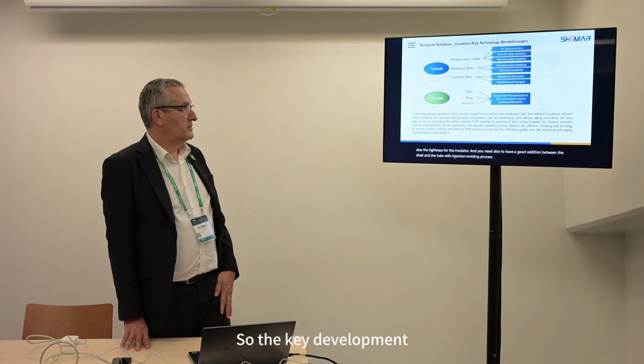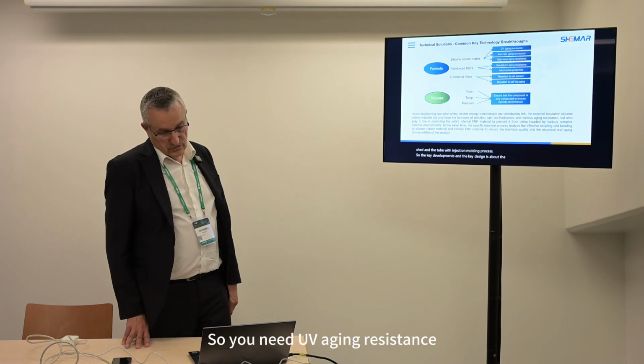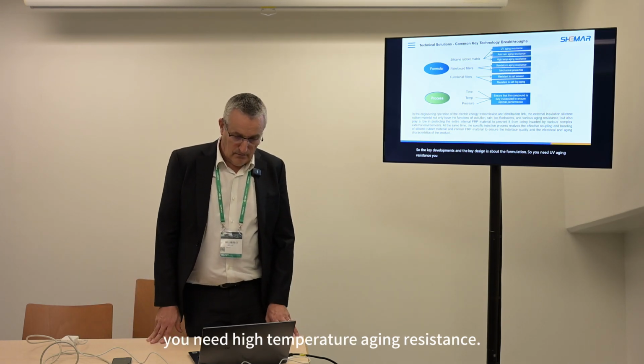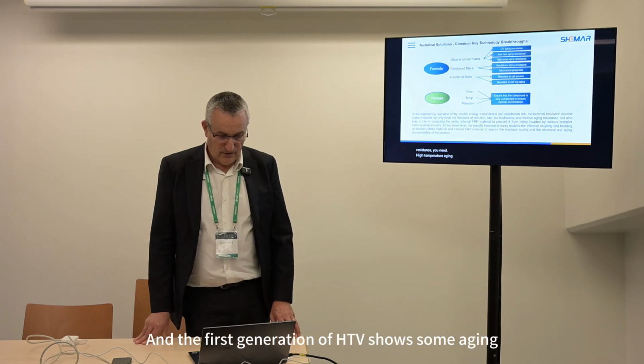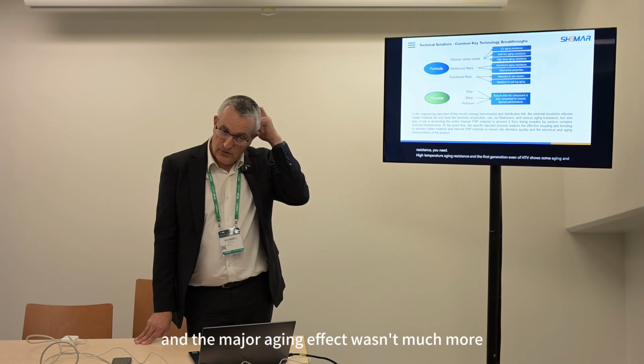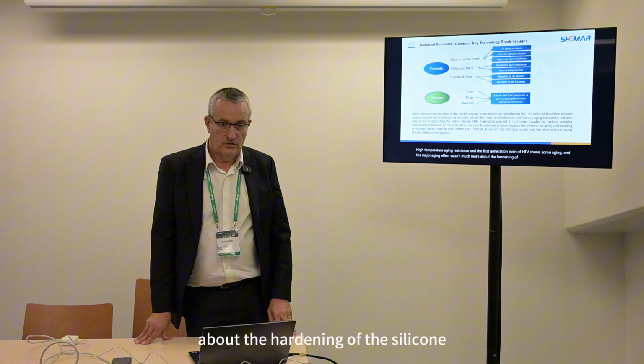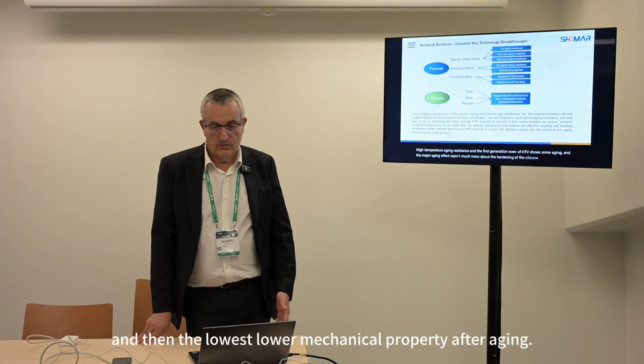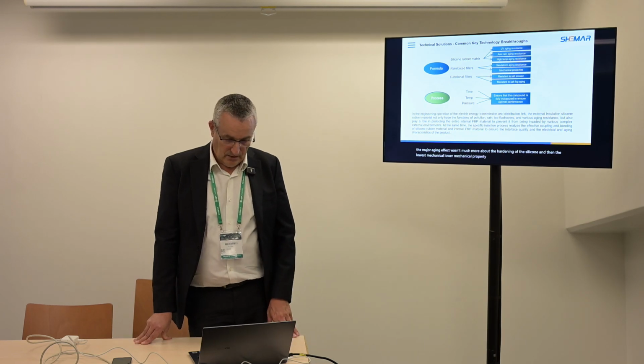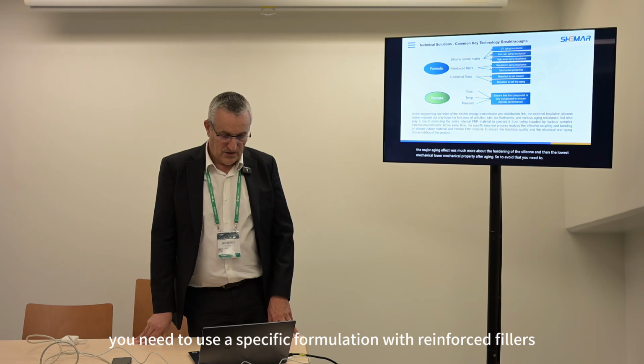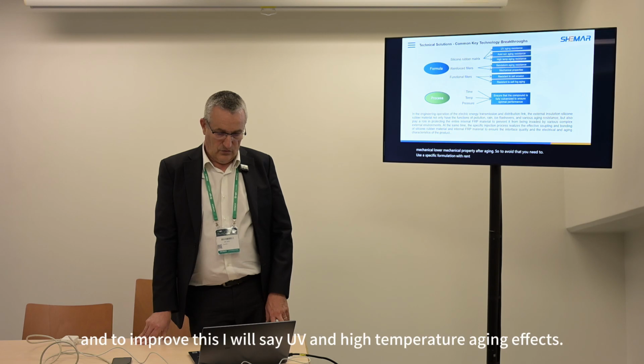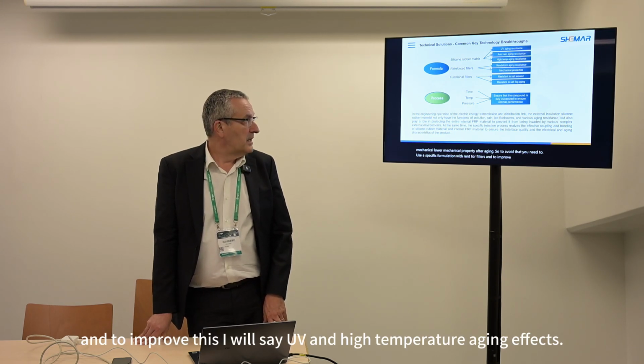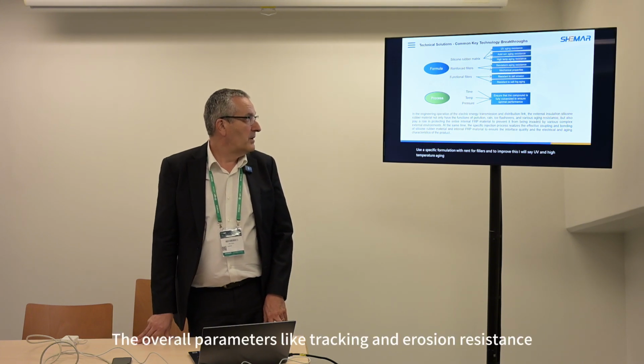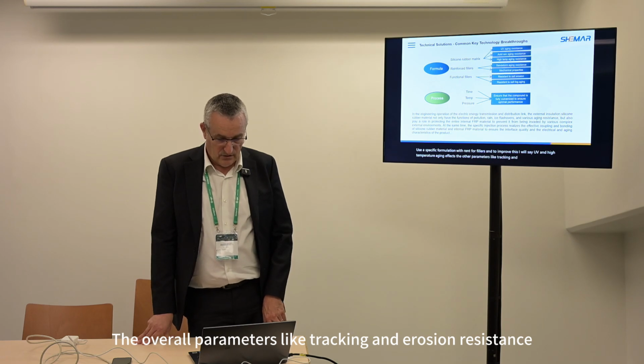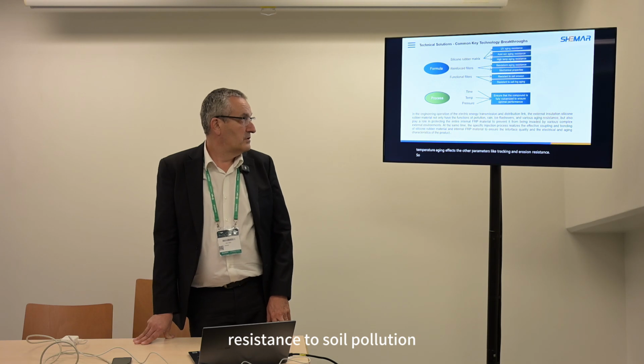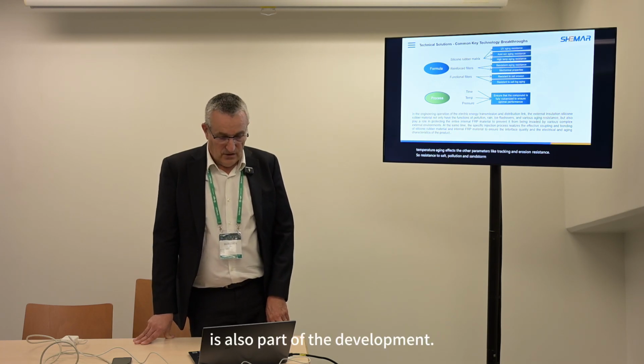So the key development and the key design is about the formulation. You need UV aging resistance, you need high temperature aging resistance, and even the first generation of HTV showed some aging, and the major aging effect was the hardening of the silicone. So then lower mechanical property after aging. To avoid that, you need to use a specific formulation with reinforced fillers, to improve the UV and high temperature aging effects. The other parameters like tracking and erosion resistance, resistance to salt pollution, and sandstorm mechanical resistance are also part of the development.